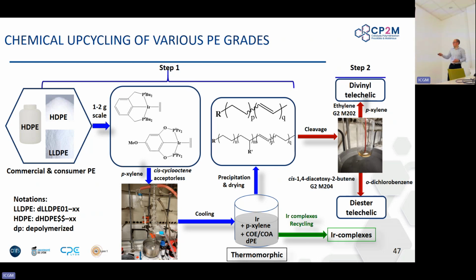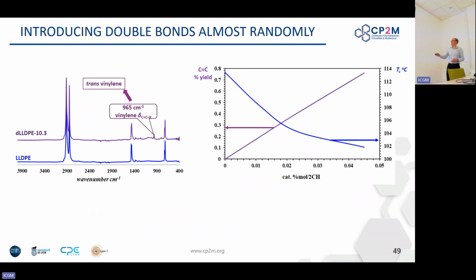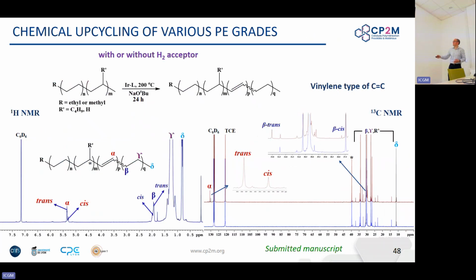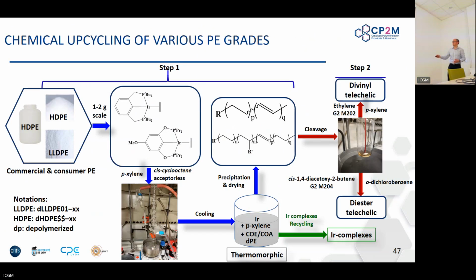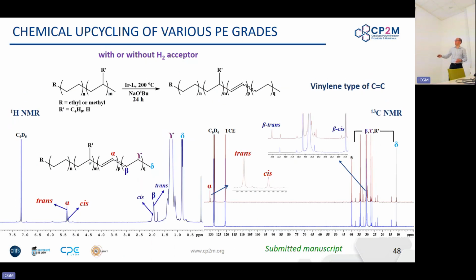So in the lab, we do that very efficiently with iridium, and we introduce trans double bonds and some cis double bonds, and this is characteristic of what iridium can do. It will usually give you a little bit more trans, especially at 200 degrees, and you have several strategies to make the catalyst very robust, and one of it is to introduce a little bit of base to prevent catalyst decomposition.